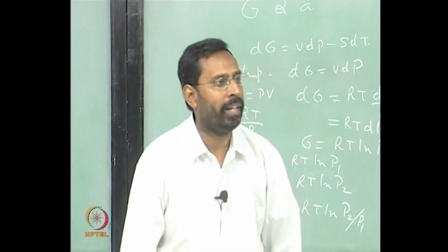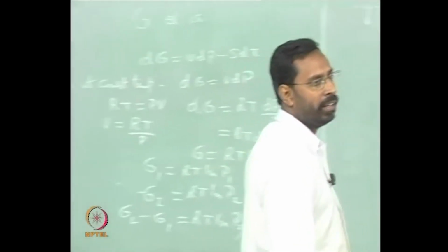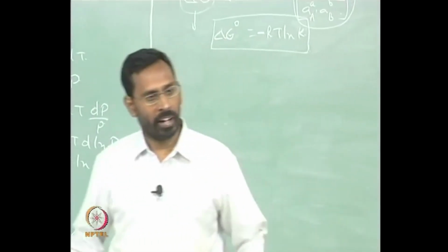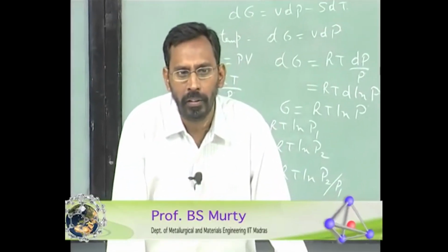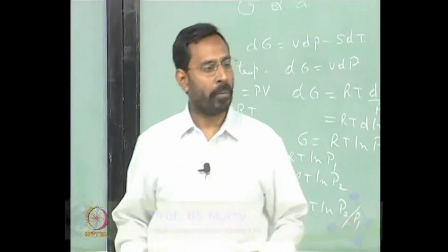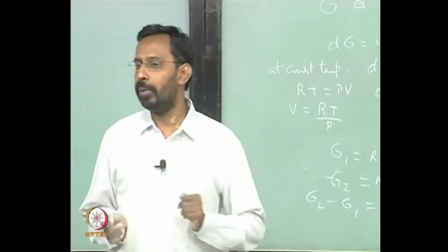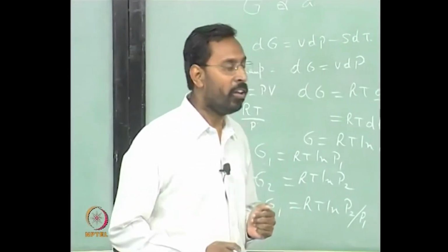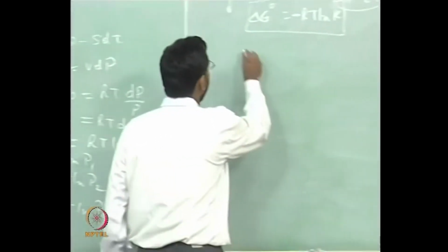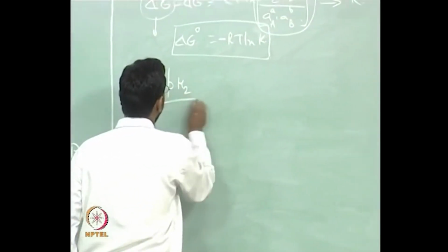Most of the time annealing is always done in furnaces which are actually heated by various oils. So, where there are always hydrocarbons, these hydrocarbons will break and give you some hydrogen, and some moisture is also expected in the reaction. So, there is what is called a partial pressure ratio pH2 by pH2O.